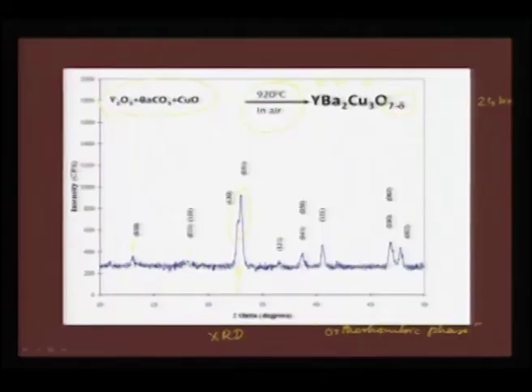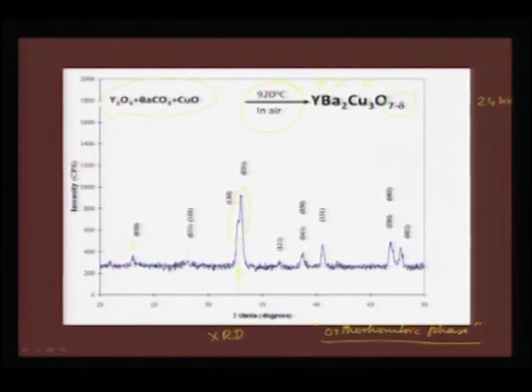particular compound very interesting, because you have labile oxygens which can be incorporated or removed, which controls the superconducting state. Therefore, this becomes a rich chemistry to achieve a fully oxygenated compound good enough to give a clear Tc at 90 Kelvin. One of the other signatures that you should follow when we look at orthorhombic phase is the splitting, and the splitting comes somewhere around 46 degree, which is indexed to both 200 or 002.